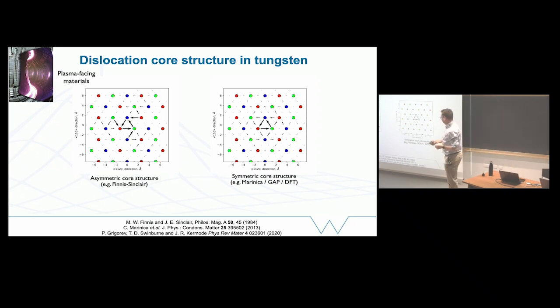And traditional interatomic potentials don't describe the core structure of dislocations correctly. If you haven't seen these figures before, this is a BCC crystal. Red, green, and blue are 3 layers in the BCC, first red, then green, then blue. And then the arrows are showing the difference in displacements in the in-plane direction, out-of-plane direction. So it's a screw dislocation, which means all the displacement is out of the plane. And you can't really see anything if you visualize it directly. So instead, this arrow here is telling us what the difference in the Z displacement of the green and the blue guy is. So it's a very compact way to show the displacement field out of the plane.